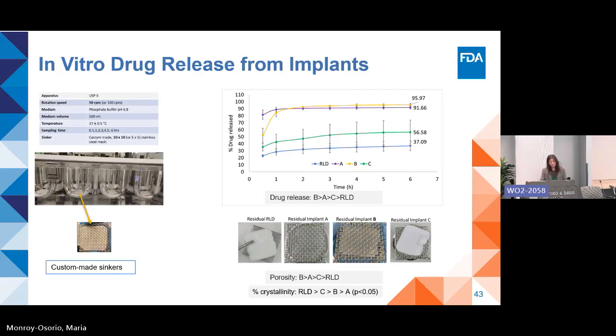Finally, the drug release study, to understand the effect of collagen sources on the performance of the implant. We have conducted the drug release study using USP apparatus 2 and using custom-made sinkers. We have investigated different configurations of the sinkers. Here, the results are provided using 10 by 10 custom-made sinkers. And these sinkers were used to hold the implant inside the release media, which was PBS buffer pH 6.8, so that the floating of the implant can be prevented during the